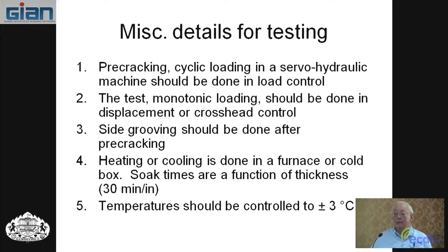What happens when you get to a maximum load and it starts to come reduced from maximum load, if you have load control and your servo hydraulic machine is demanding more and more load, when you get to a maximum load, it just rips everything apart. So you can't get the full load and displacement curve in load control, but load control is good for pre-cracking.